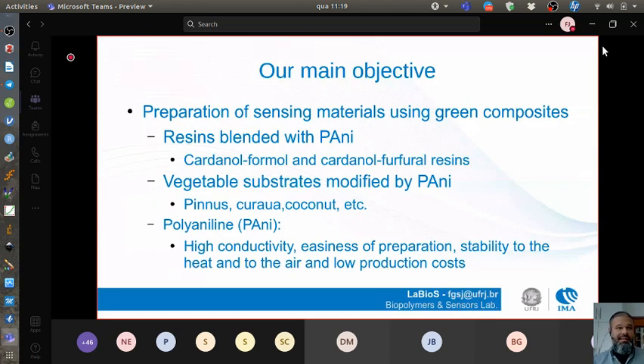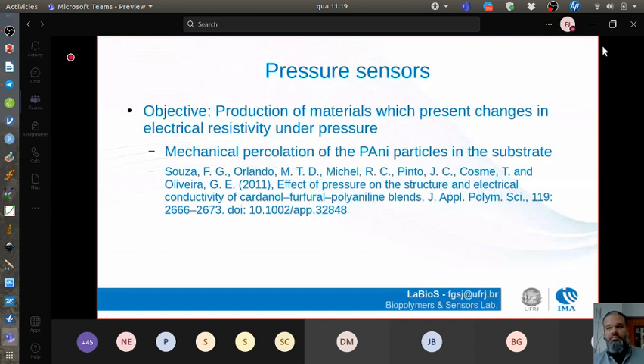We perform this not modifying the substrates. In this case, we prepared a blended material. This blend was prepared using cardanol formol and cardanol furfural resins. In both of them, we inserted different amounts of PANI, and then we tried to understand what was going on with the physical properties of these materials. So, one of the first works related with this was this one, the mechanical percolation of PANI particles in a substrate, which was cardanol furfural resin.